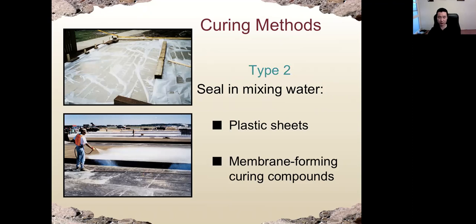The second type of curing is we do not provide additional water, but we seal the concrete by using plastic sheets. Like here, what we use, we call that membrane-forming curing compound. Here, the spray is not water; it's a membrane-forming curing compound, which forms something like plastic sheets, so the water from the concrete will not evaporate.